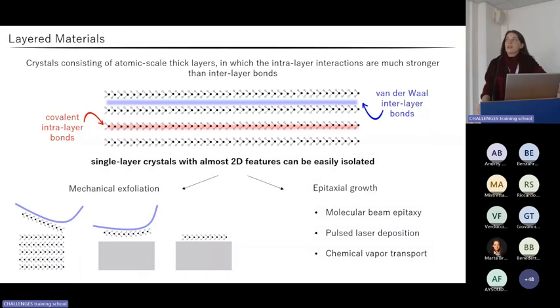Let's start with a brief introduction about the samples under consideration. Two-dimensional materials are layered crystals in which the intra-layer interactions are mostly covalent in nature and therefore much stronger compared with the interlayer bonds, which instead are mostly ruled by weak van der Waals interactions. Due to this peculiar structure, it is relatively easy in two-dimensional materials to isolate single-layer crystals with atomic scale thickness and therefore a quasi-two-dimensional nature.